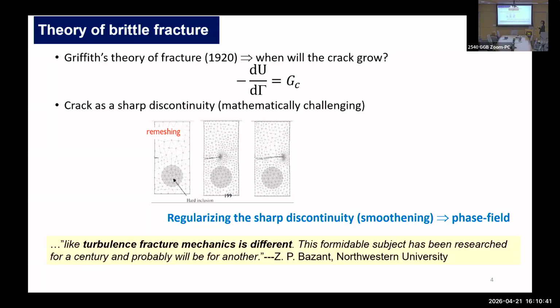or the stored strain energy released per unit area of crack equates the material's fracture resistance, or formally known as fracture toughness, then that determines the unstable crack growth criteria. And this was very simple and widely applicable to describe the fracture behavior of brittle material. And of course, based on Griffith's seminal work, there has been a significant volume of work in fracture mechanics because it's challenging to deal with it as the material constitutive description changes from brittle to ductile, then heterogeneity and anisotropy, etc.